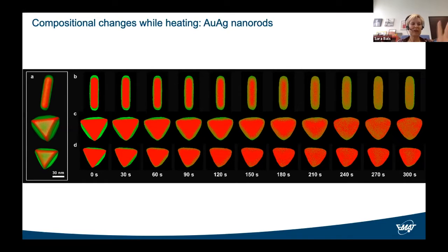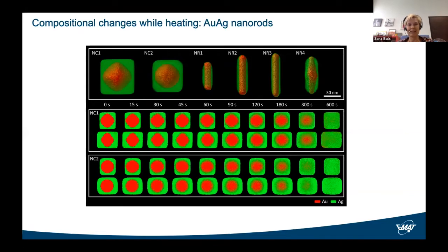And we also, because of these subtle changes, performed another study where we have compared 6 different nanosystems. So we have 2 nanocubes, and the nanocubes, they have a different core morphology. There's one type of nanocubes with an octahedral morphology, the other one has a spherical morphology, and so that enables us to understand the role of the type of interfacial facets. Then we have 4 nanorods. Nanorod 1 and 2 are single crystalline. They have a difference in size. And nanorod 3 and 4, they have a pentatwinned core. So nanorod 3 has a rod-like core morphology, and nanorod 4 has a bipyramid morphology.